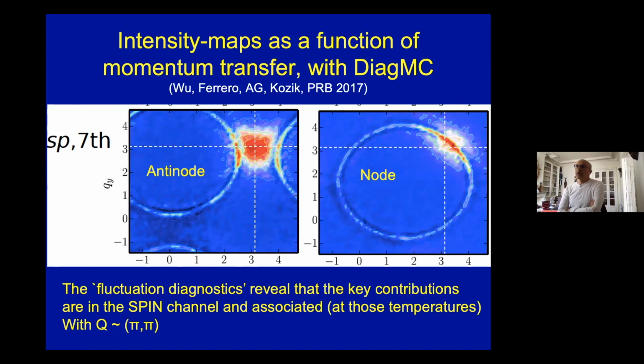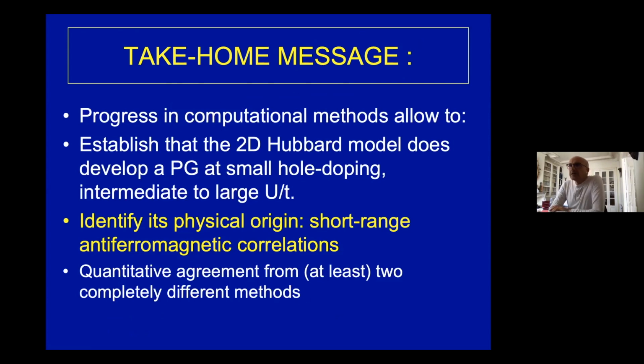In this work with Wei Wu, we actually applied this method and demonstrated that the pseudogap is actually due to Q equal pi correlations associated with antinodal physics. So it's really the physics of commensurate antiferromagnetic correlations with not a very large correlation length, which is responsible for the pseudogap opening. So the take-home message of this part is that actually progress in computational methods, both diagrammatic Monte Carlo and cluster extensions of DMFT, allow us to establish that the 2D Hubbard model does develop a pseudogap at small hole doping in the intermediate to large U over T regime, and that its physical origin is short-range antiferromagnetic correlations, not other types of correlations.